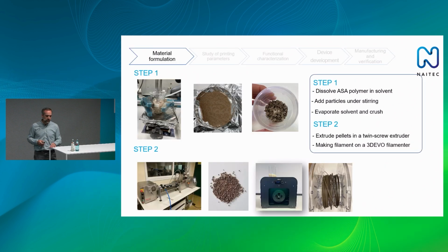In order to obtain a conductive filament from this material, this is more or less basically the process that my coworkers follow to functionalize it. First, they need to dissolve the polymer in order to incorporate the metallic particles that will give the conductive properties to this material. Second, when all the mixture is homogenized, the solvent is removed from the mix, so we have a hard mixture of polymer and particles that's broken down into small pieces. And then in the second step, we do the filamentation. First, we use a twin screw extruder to obtain some pellets, and then feed a 3D EVO filamenter with these pellets. And finally, we obtain a filament that has very good conductive properties.